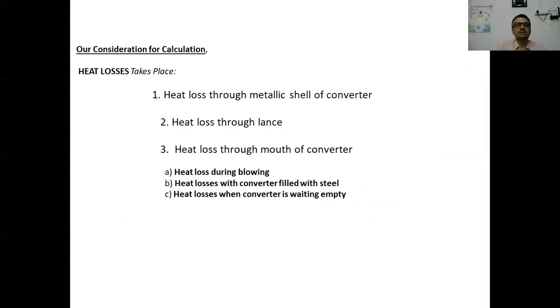So we made the following considerations for our calculation: heat losses take place through conduction through the refractory lining, followed by radiation from the outer shell, then the heat loss through the lance, then the heat loss through the mouth of the converter. We have developed a separate model for the heat loss calculation, and based upon the design parameters of the converter, which have been provided by the industry, we have calculated the heat loss during blowing, heat losses with the converter filled with steel, and heat losses when the converter is waiting empty.